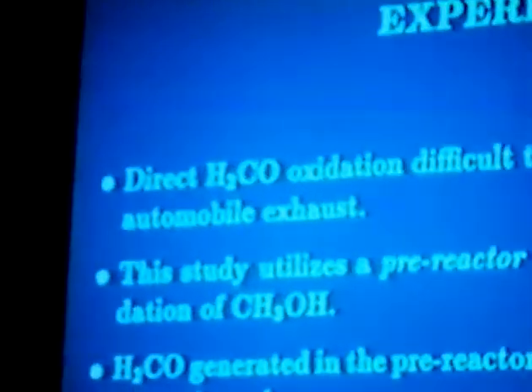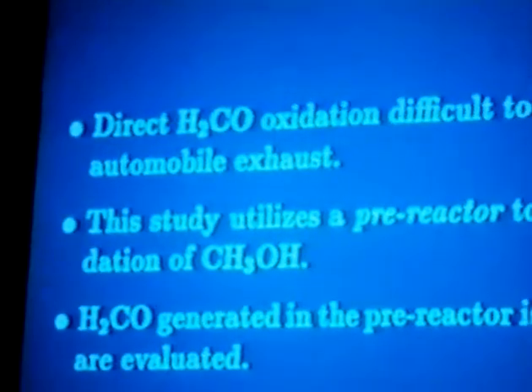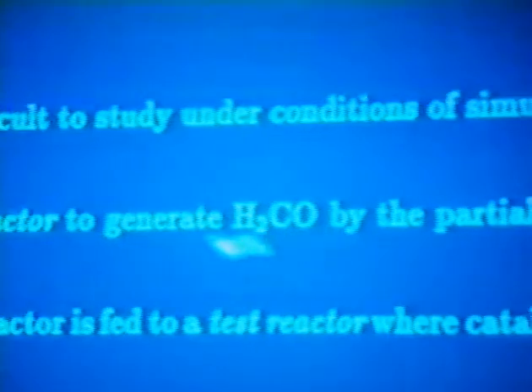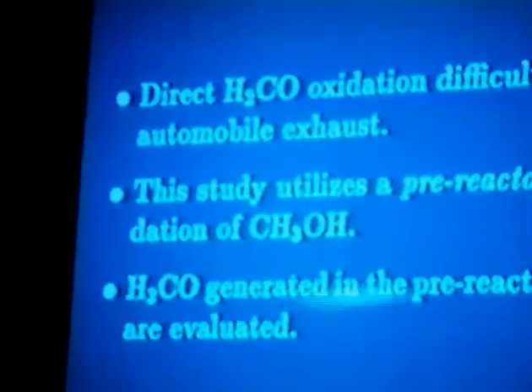Experimentally, the direct formaldehyde oxidation is difficult to study because it involves having to make gaseous formaldehyde, and your options are either starting from paraformaldehyde or starting from a formalin solution. Neither one was very attractive to us because of the difficulties of maintaining formaldehyde in vapor state. So as an alternative, we utilized a pre-reactor to generate formaldehyde by the partial oxidation of methanol. And then we fed that formaldehyde from the pre-reactor into a test reactor where the catalysts were evaluated. And the scheme is shown here.